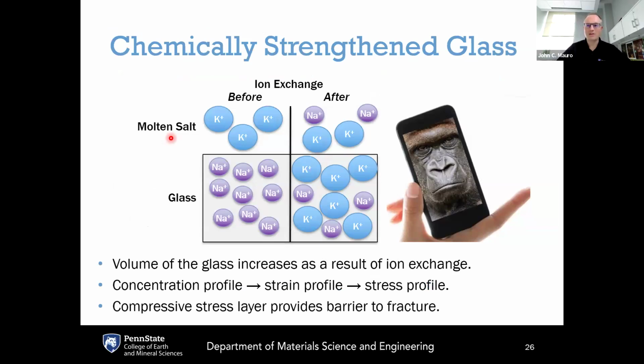This involves taking the glass, submerging it in a molten salt bath at a temperature of about 400 degrees C. What happens is that the smaller ions from the glass, like sodium, will diffuse out into the salt bath. They get replaced by larger ions like potassium from the salt bath. The larger ions want to expand the glass surface, but they're unable to because the interior of the glass is keeping them within a certain geometry. And so this concentration profile of potassium gets converted into a strain profile, which gets converted into a stress profile. And this gives stresses on the order of about 1 gigapascal. So it's much higher stresses compared to